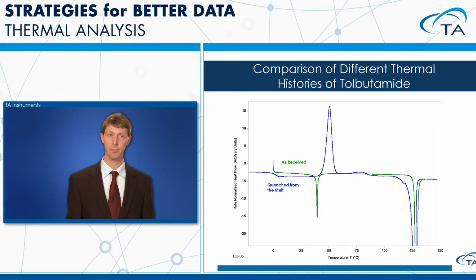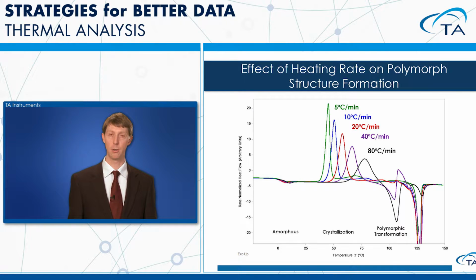So that's really how you're going to be able to differentiate the composition of materials with a heat-cool-heat experiment. Now, in this particular case, we're actually forcing the material into different forms with changing heating rates. There are materials that, given enough time, will change into a multitude of crystallization states. They're typically called polymorphs. And so you can see that in this case, at 5 degrees a minute, we're spending a lot of time at temperature. We're just slowly increasing temperature such that it goes through a crystallization, and then it has the ability to go through a variety of different